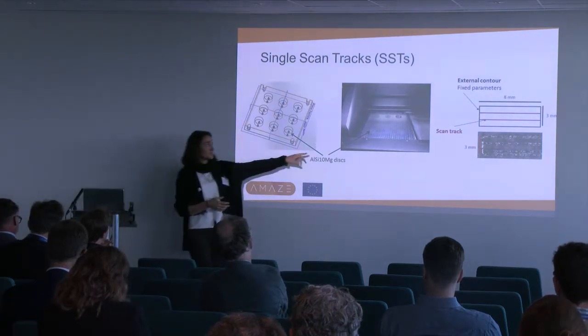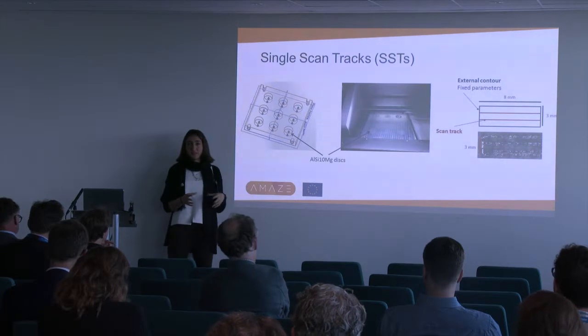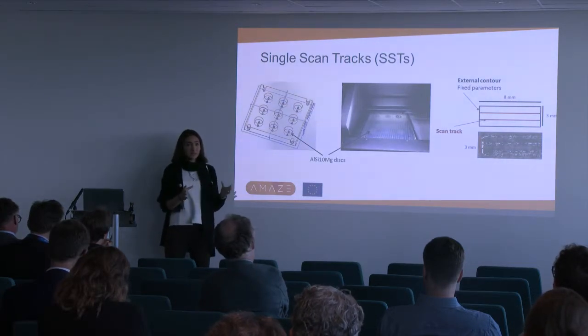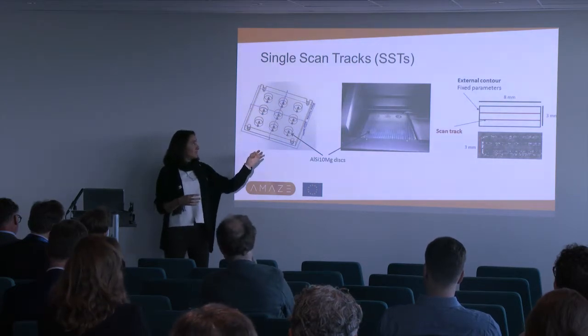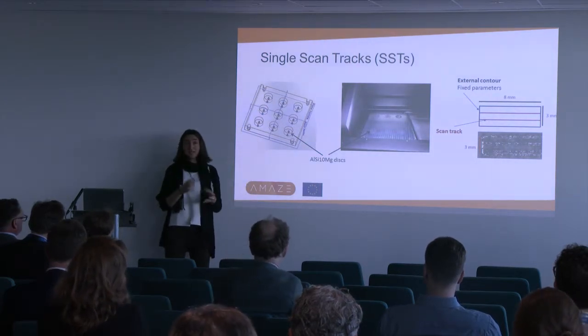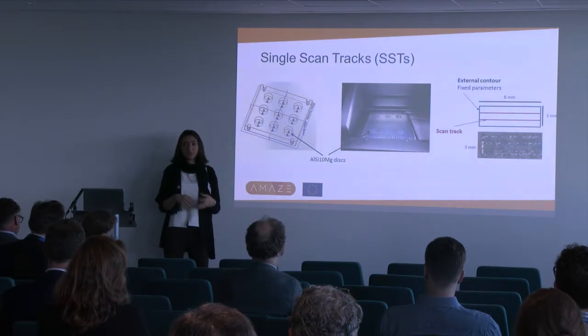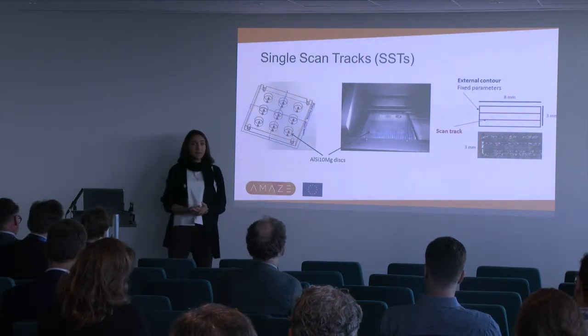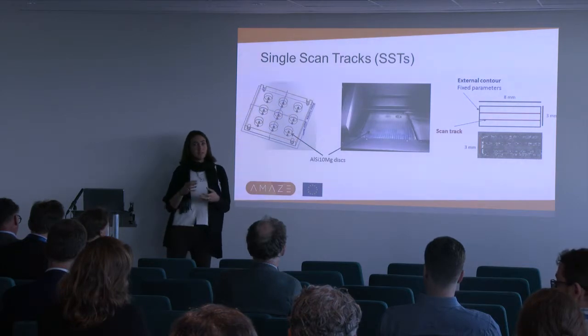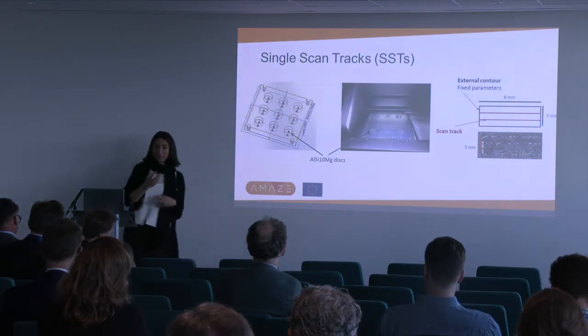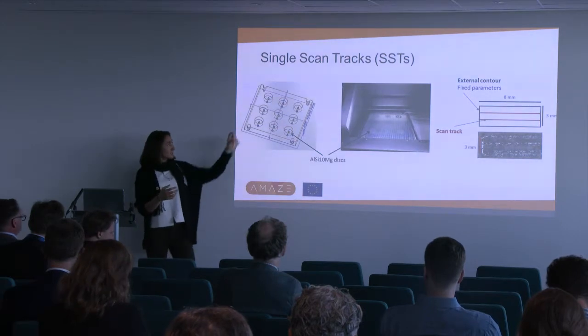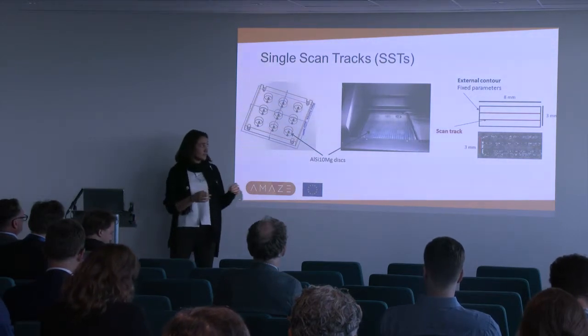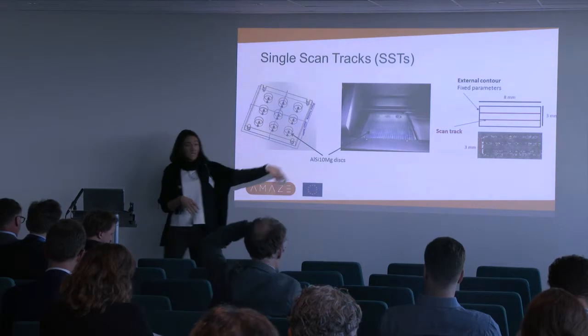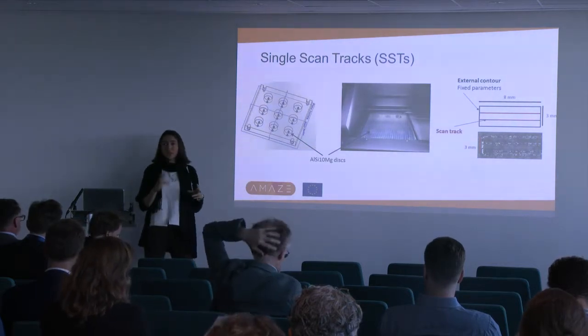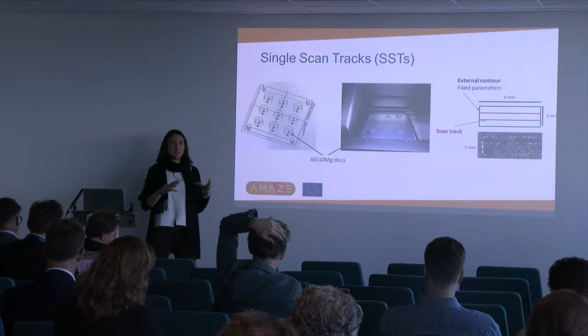This is the inside of our machine. We built a modified building platform. The platform was made of aluminum magnesium alloy, so we had to build some discs made of the same material, or at least a similar material, in order to have similar properties, such as the thermal conductivity and everything. So we made these discs, which are aluminum silicon 10, put them in the machine, and we also had to find a way to tell the machine to design only a single scan.